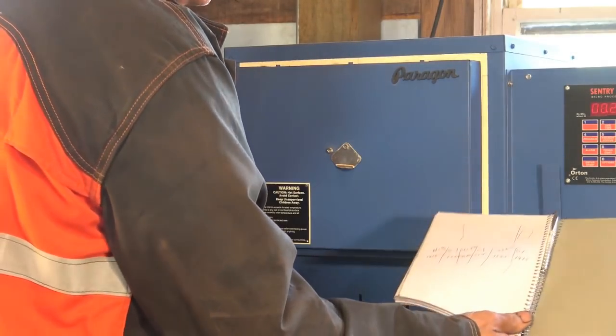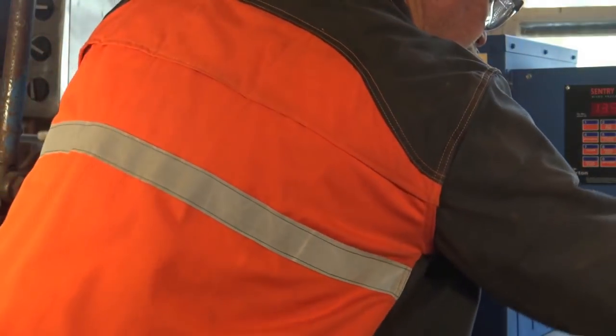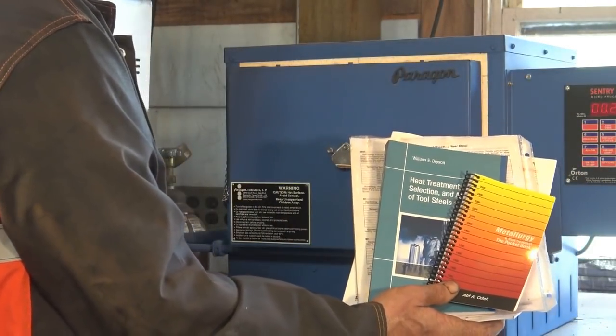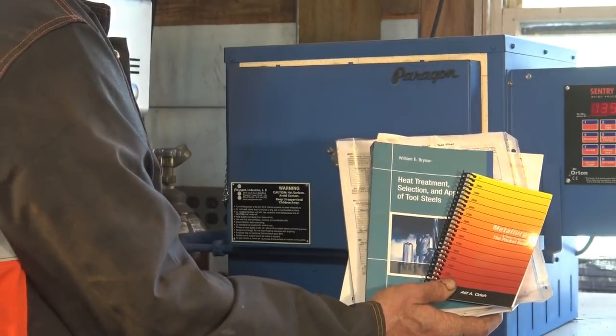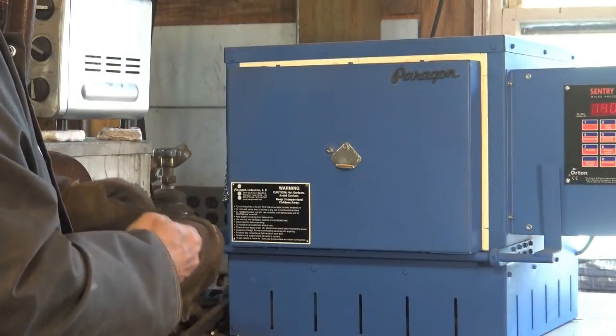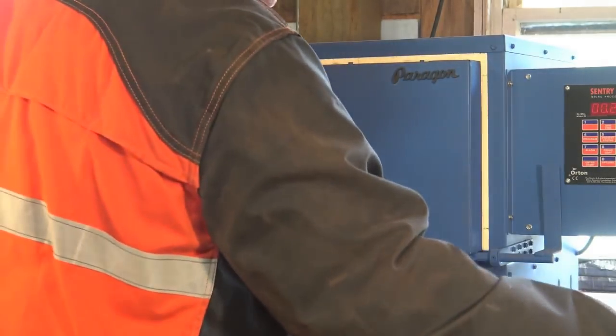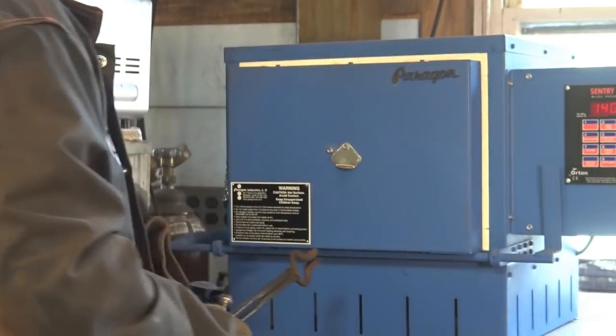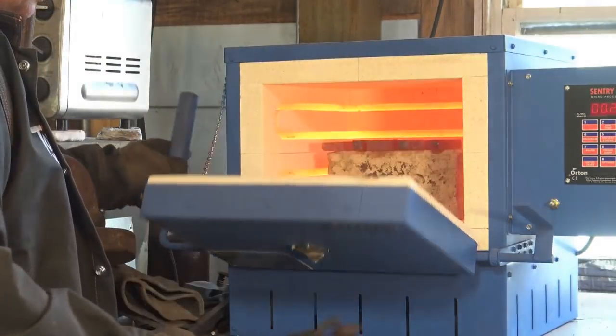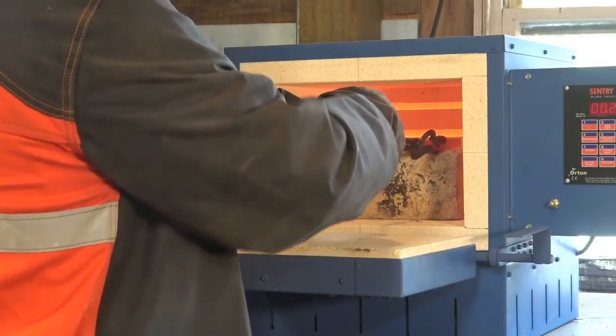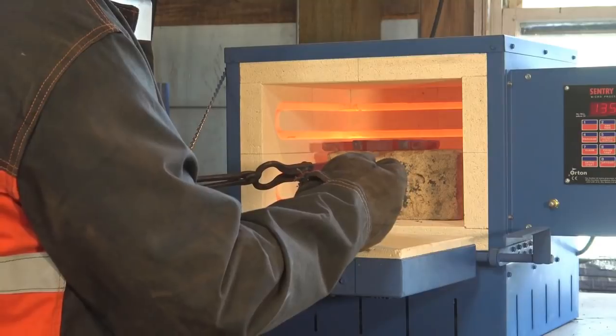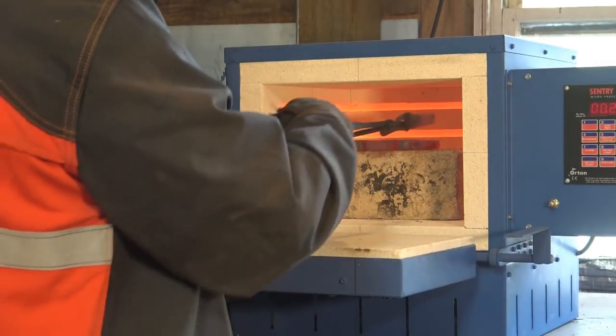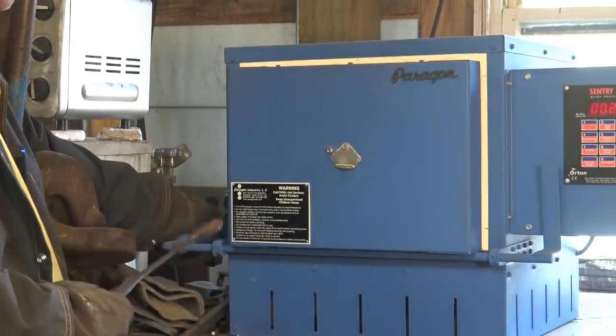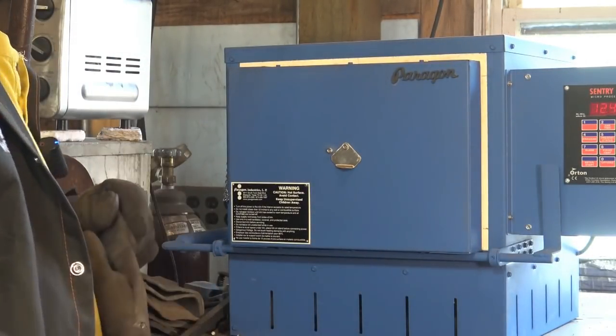Now, while this was heating up, I took the time to write down the critical temperatures of all the steels based on my reference information, and these are all books and sources we have talked about before. So I know W1 is 1475, and we're at 1400 right now. So we're way too cold, 75 degrees too cold for W1 to harden. But is it still magnetic? And it has already lost magnetism. I don't know where it lost magnetism, but the W1 is no longer magnetic at 1400 degrees. So that means it's at least 75 degrees more to get to critical temperature.